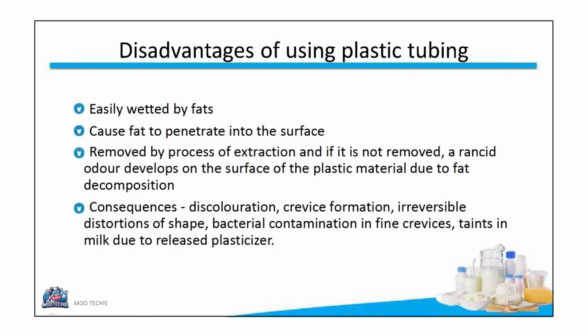However, there are disadvantages to using plastic tubing. It is easily wetted by fats. This can cause fat to penetrate into the surface of the plastic. This fat is very difficult to remove, and if it is not removed, a rancid odor develops on the surface due to fat decomposition. The consequences include discoloration, crevice formation, irreversible distortions of shape, bacterial contamination in those fine crevices, and taints in the milk due to plasticizers leaching out from the material.